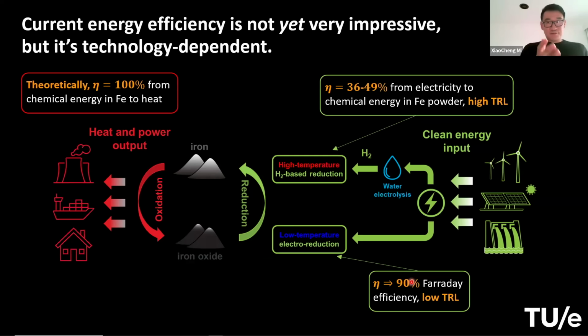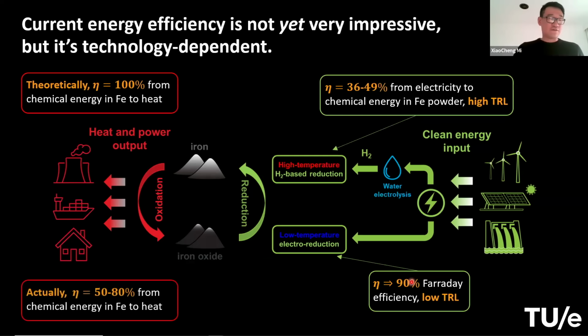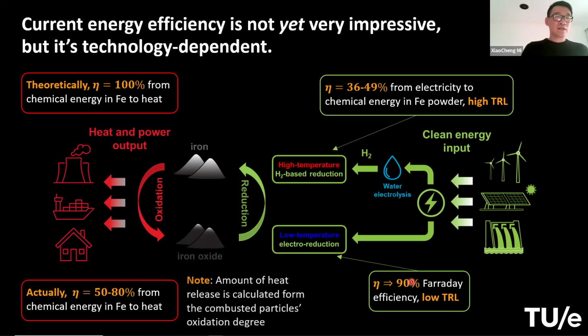But as a combustion scientist, I care about the combustion side, right? Theoretically, if you burn a fuel, you can fully burn it. It can all go into heat, right? Thermodynamics allow us to do that. However, as you can find in Nick's PhD thesis, so far, depending on the conditions, the iron chemical energy to heat efficiency varies from 50 to 80%. So not ideal, but theoretically, we should be able to 100% extract this amount of energy as heat. And also please note this efficiency is calculated based on the oxidation degree of the material we collect after combustion. So the lack of efficiency is not due to the technology of a heat exchanger, right?